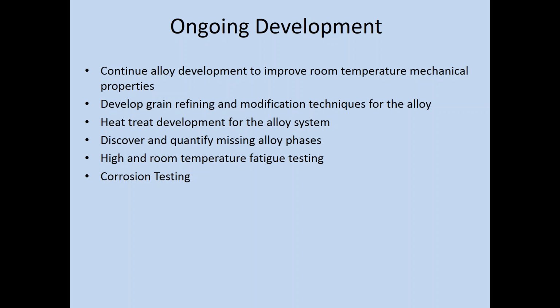Again, in general, because cerium slows the diffusion of almost all the elements involved, we will likely need to heat treat at fairly high temperatures in order to get anything to move. And we're still trying to discover and quantify missing alloy phases that should be there, but we're not seeing, but we know they're there because of the effect they have.